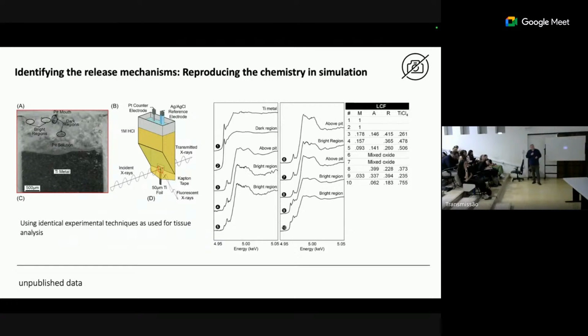And we say to ourselves, well, can we prove that you could generate those in physiological fluids in a way that would potentially happen in the body? So again, one of the remarkable things about the instruments that I'm using is I can go from one day mapping tissues to the next day having an electrochemical experiment where I'm doing in situ dissolution of titanium in biological fluids. And by modifying those biological fluids, we then built up a picture that we could explain if we put in small amounts of reactive oxygen species, say, transient peroxide, that you could actually start to produce these. So under pseudo-inflammatory conditions, you can account for titanium in solution for a very short period of time.